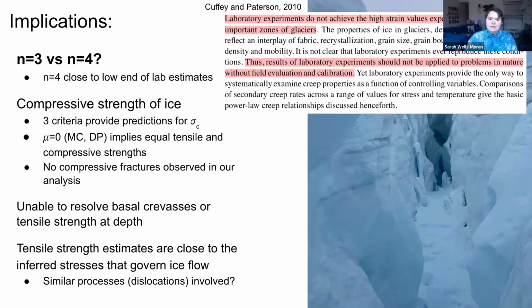And this 250 kilopascal discrepancy between observations of tensile strength when n equals 3 and lab estimates of tensile strength has previously been explained with damage in natural glacier ice or other discrepancies between the lab environment and actual ice. But with these n equals 4 estimates, I think it brings us a lot closer to reconciling this previous massive gap in lab estimates versus field observations. So I am a little biased towards the n equals 4 side, but I think it's pretty cool that our n equals 4 estimates for tensile strength are pretty close to that low end of lab estimates.